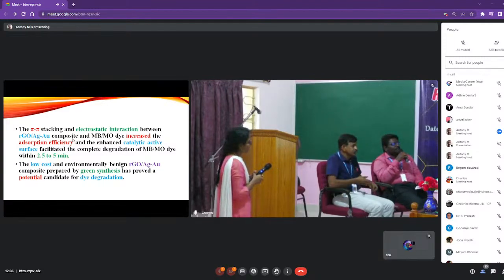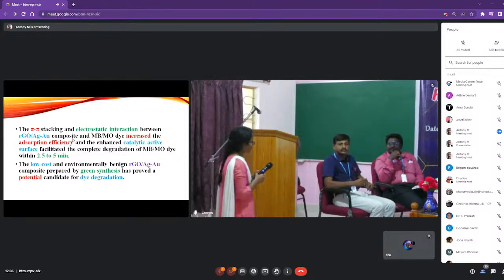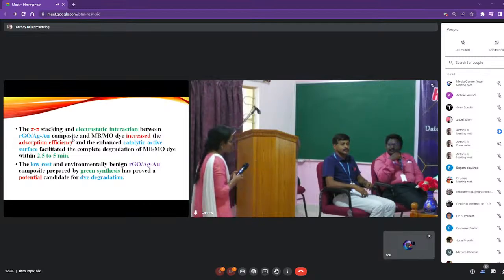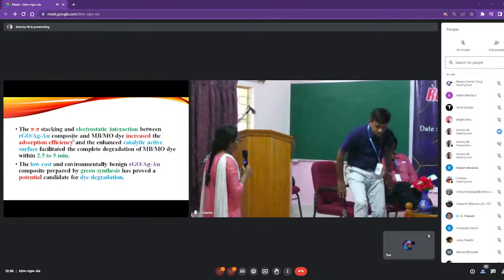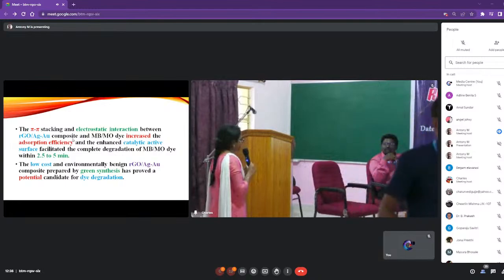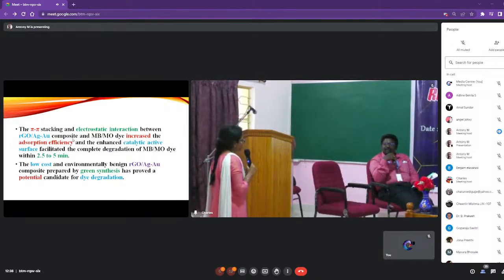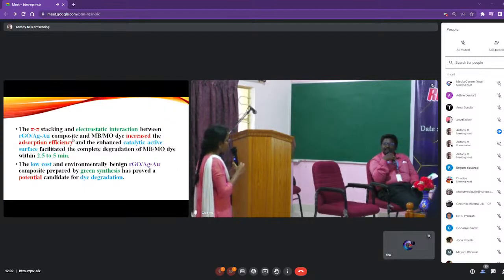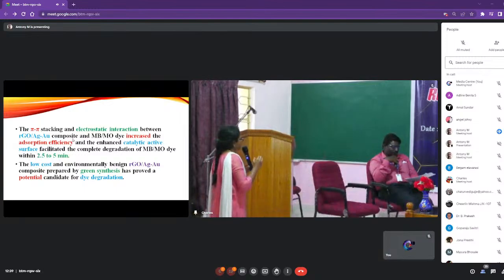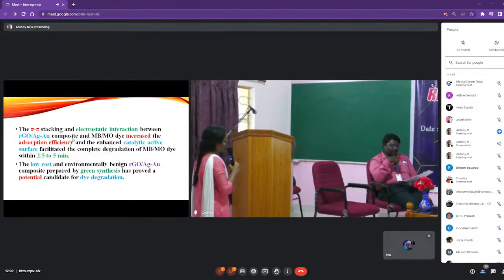In the XRD pattern, you have shown A, B, C, and so on. A is the pure graphene oxide, and the next one is reduced graphene oxide. There is a shift. What is it? Oxygen-bonded molecules are more reduced, so there is a shift from 10 degrees to 24.7 degrees.